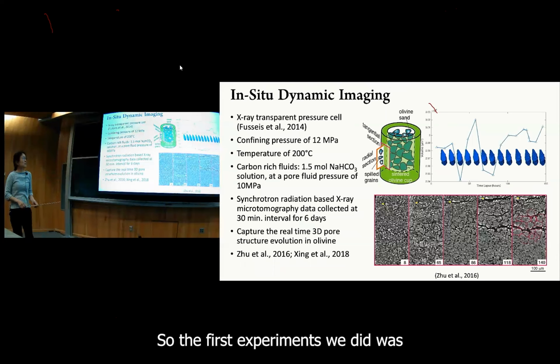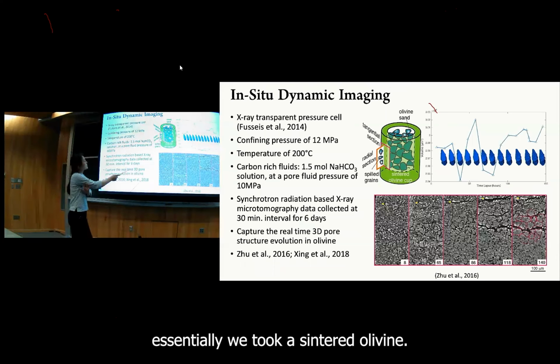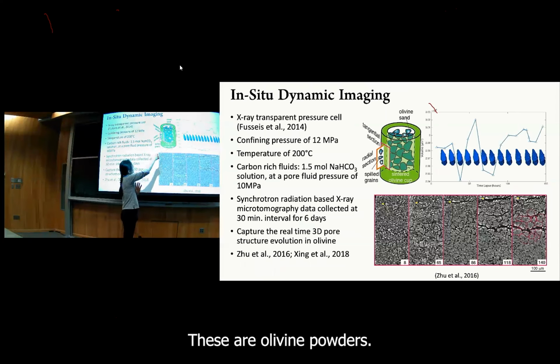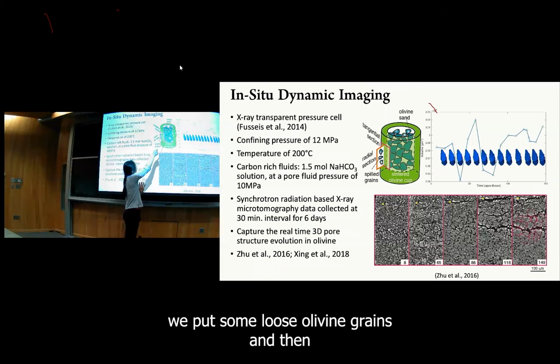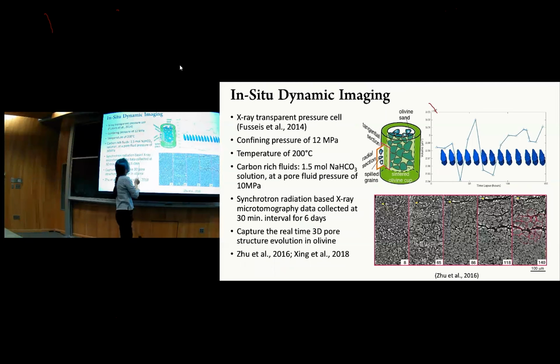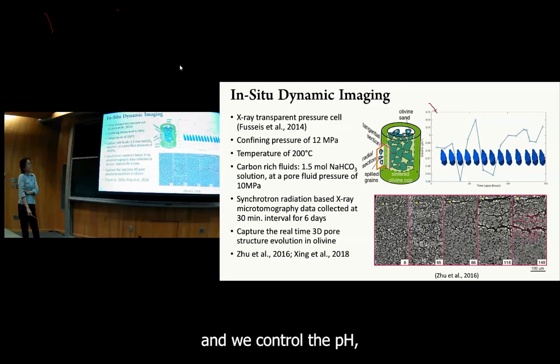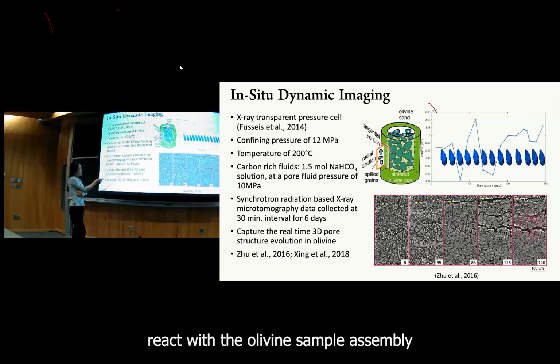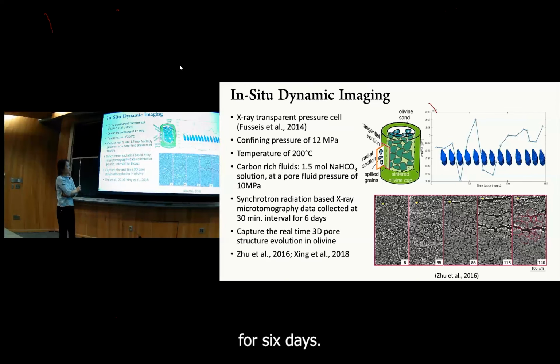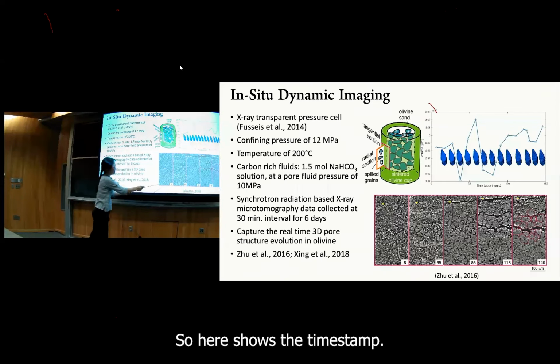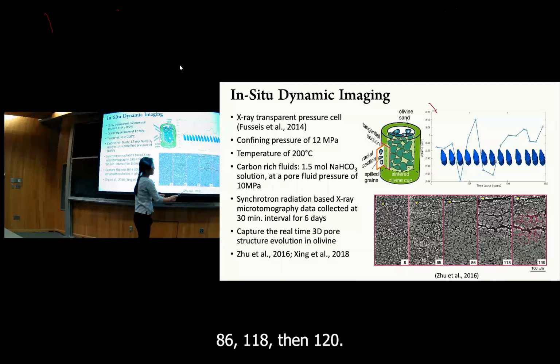So this is some of the technical aspect of it. The first experiment we did was essentially we took a sintered olivine. These are olivine powders. We sinter it and built an olivine cup, and inside we put some loose olivine grains, and then let them react with 1.5 molar NaHCO3. With that bicarbonate, we control the pH about 8, and so this is a saline solution with carbon-rich ions. And then we let it react with the olivine sample assembly for 6 days. Every half an hour, we collect the 3D microtomography data. So here shows the timestamps: 8 hours, 65, 86, 118, and 120.